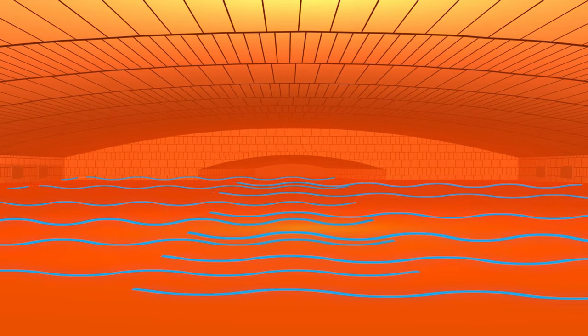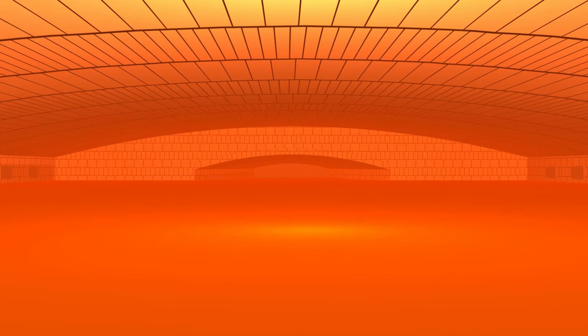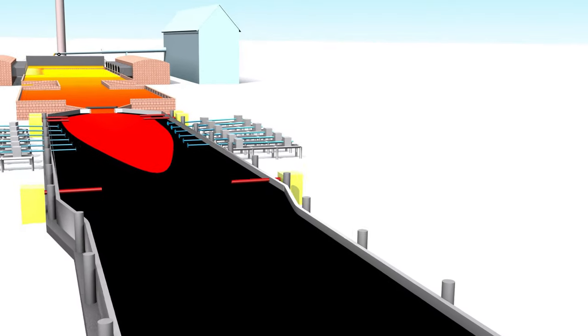Glass is then ready to leave the melting furnace and enter an enclosed bath of molten tin. At that point of the process, the glass looks like honey. At the beginning of the float bath, glass coming from the furnace flows gently and spreads out, literally floating on the molten tin, to become a continuous ribbon of perfect flatness. The edges of the glass puddle are mastered by top roll machines, which act on the spread surface of the glass. The top rolls' effect, together with the exit speed of the ribbon, are the two main factors used to adjust its thickness and width.